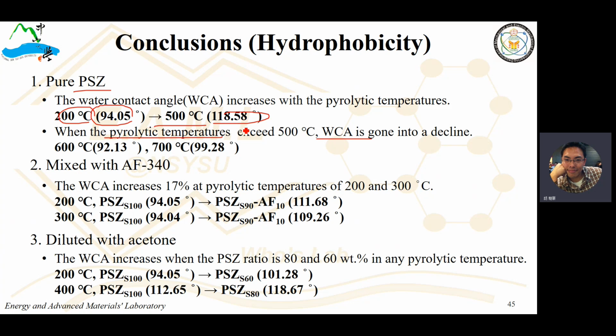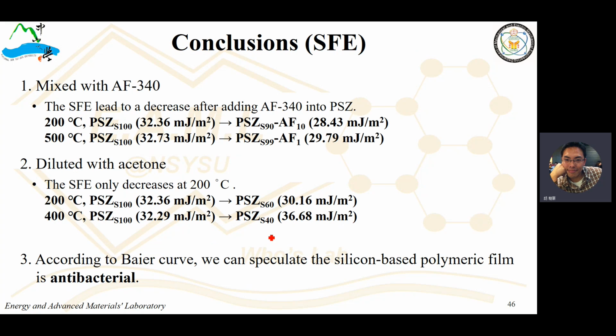When this precursor is incorporated with the fluorinated resin F340, the contact angle increases 17% at a temperature between 200 and 300 Celsius. When the PSZ precursor is diluted with acetone, the contact angle increases, and the optimal ratio is 60% dilution in acetone. However, its surface energy is not the lowest. It even becomes higher. And when this precursor incorporates F340, its surface free energy is reduced.